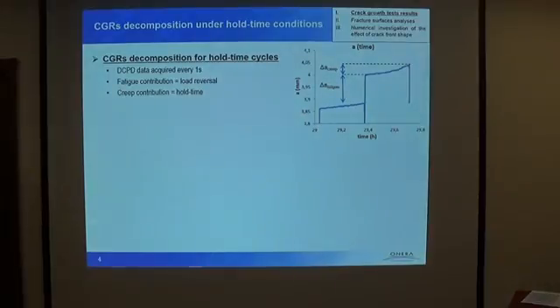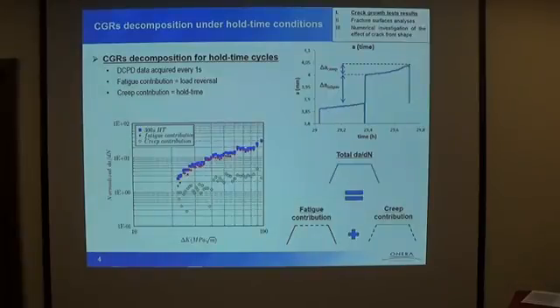Okay. In order to investigate the fatigue and the creep contribution, we decided to acquire continuously the DCPD signal in order to extract the crack lengths occurring at load reversal. So this is the fatigue contribution. And the crack increment occurring during the hold time itself, this is the creep contribution. So with this, we are able to get three da/dN versus delta K curves from one test. You have the blue one, which is the classical da/dN versus delta K curve considering the whole cycle. We have the red one, which corresponds to the fatigue contribution only, and it represents, let's say, 90% of the crack propagation. And finally, the green one, which was extracted from the hold time itself.